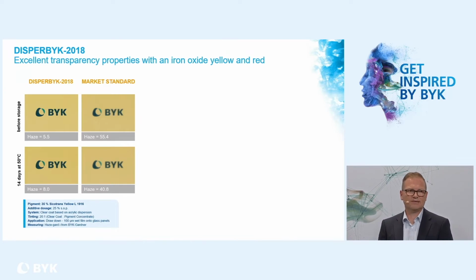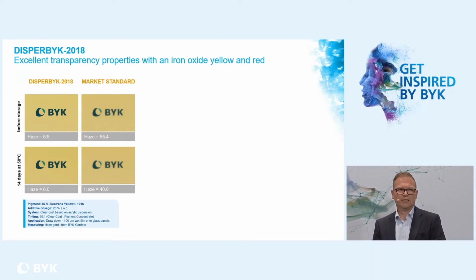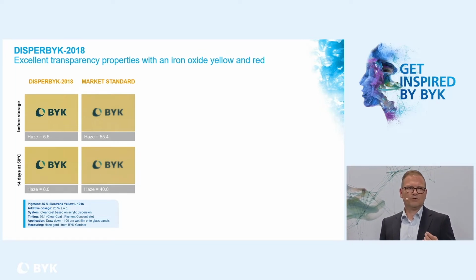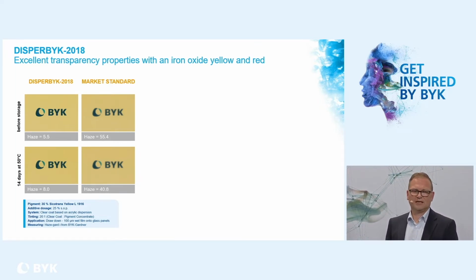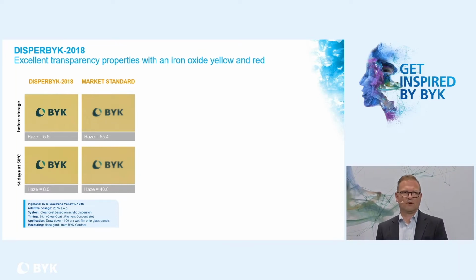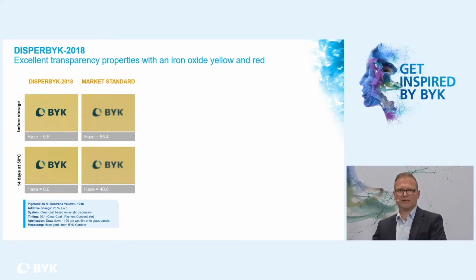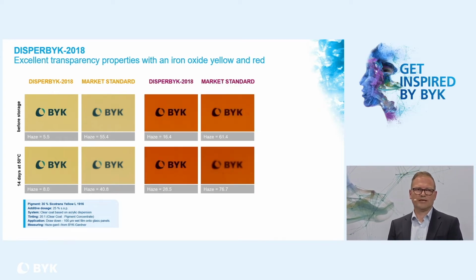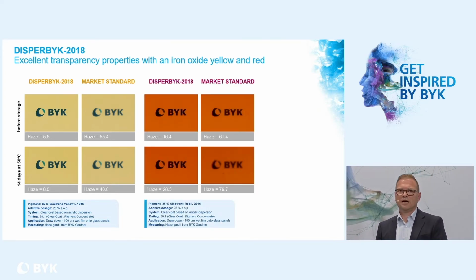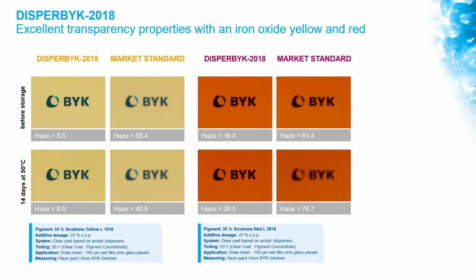Transparent iron oxide, the next example. First of all, iron oxide yellow. You see here with iron oxide yellow in a wood coating formulation, the really high clearness, the good transparency, the brilliance of the paint formulation just after production of the pigment concentrate and then added to the base paint, but also after storage. And sometimes you see it here much better. After storage, this could be the problem. On the right-hand side pictures, you see that after the storage, the haze value is increased and the transparency is decreased. Means the long-term stability is not given with the market standard. With DISPERBYK-2018, over a long time, you achieve the same good performance.